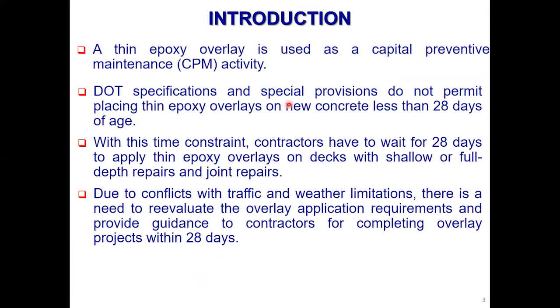So typically we use epoxy overlays as a capital preventive maintenance activity. In order to apply these overlays, DOT specifications and the special provisions require the contractors to wait until at least 28 days. So this conflicts with the traffic and weather limitations. So we wanted to reevaluate whether we can apply these overlays before the end of the dry curing period. That means before the end of the 28-day age of concrete.